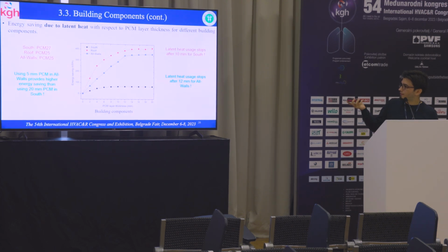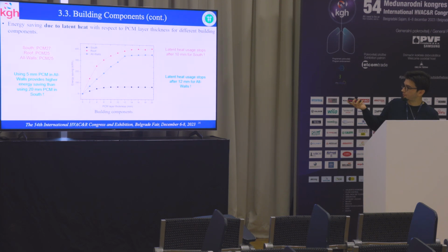And this is the energy saving. It is the same, but due to latent heat activation. As we can see here, in the all walls case, the energy saving due to latent heat activation nearly stops after 12 millimeters.